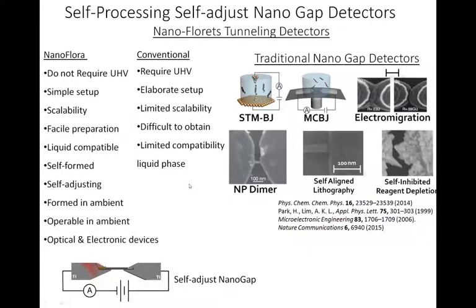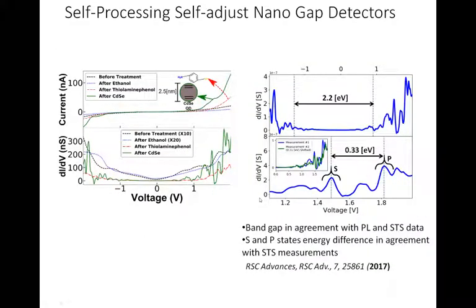So this was the first demonstration of such nanogap detectors. And what we did here, we took amine thiol molecules, and we took some cadmium selenide quantum dots, which have a specific band gap and fine structure. And we could really show that the density of states, the dI/dV, as a function of applied voltage in this device, is responsive towards the chemical species that are entrapped while you simply put a drop on it. And you can see here the typical gap for the quantum dots and even fine structure of the SP transitions. All of this was measured in ambient conditions.